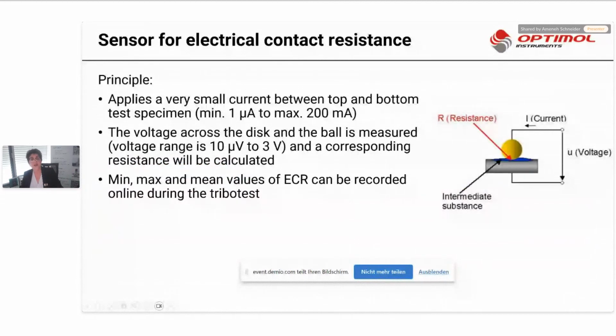Short, very, very short, one slide about this sensor. It's very, very simplified here, the principle. We apply a current, very, very small current between 1 microampere to 200 milliampere. In the upper specimen is a ball, lower specimen the disc, and it goes through this intermediate, which can be oil or greases. And the voltage across the disc and the ball is measured, which is also approximately 10 microvolts to 3 volt, and the corresponding resistance would be calculated from the software, and you have this value in 3 forms: minimum, maximum, and mean value. We are going to see on the next example always the mean value.